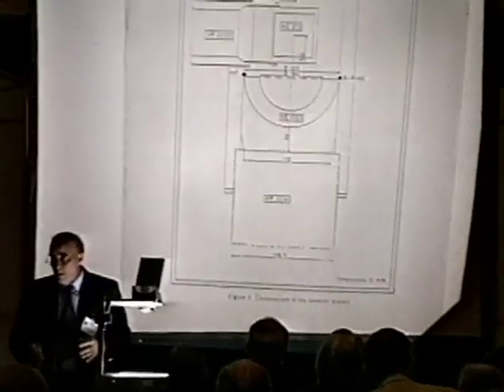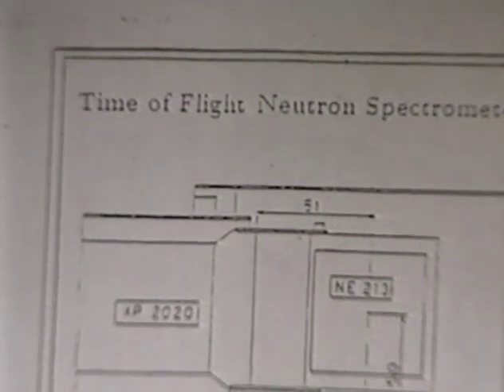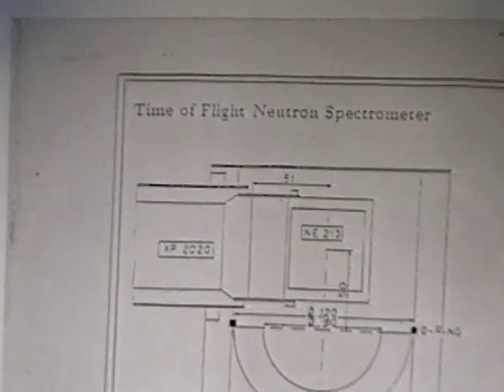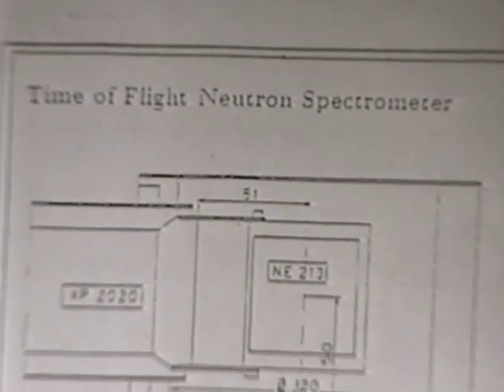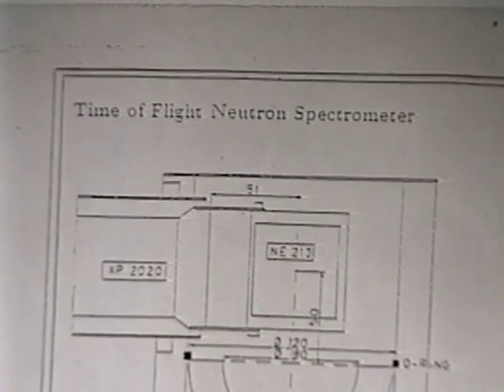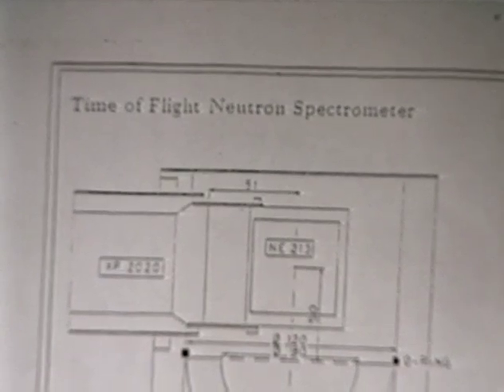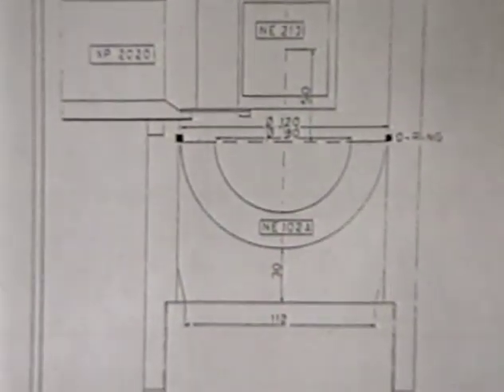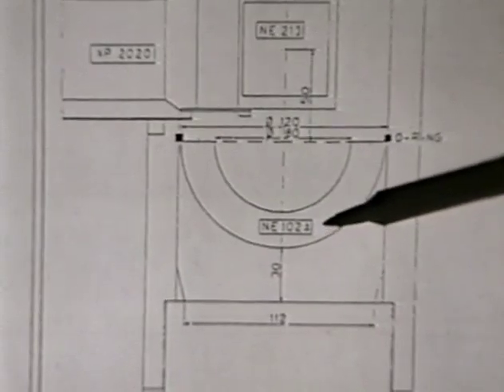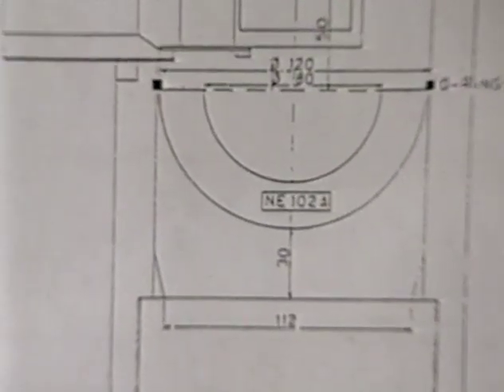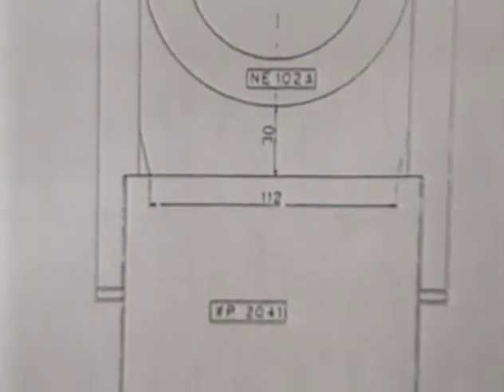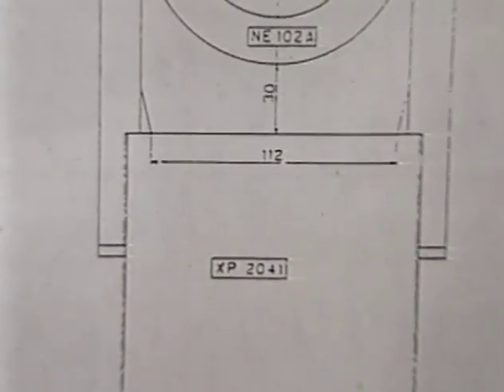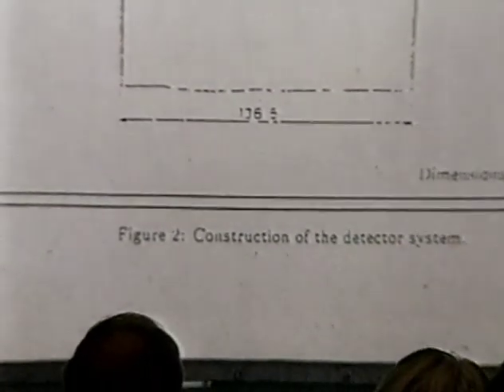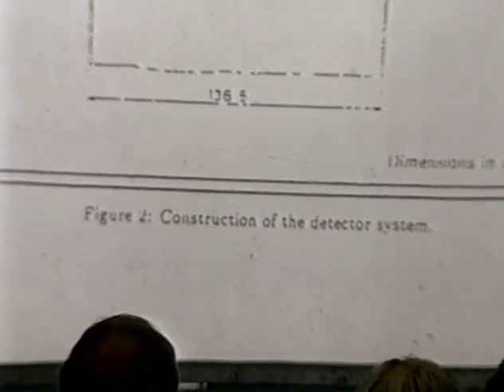We will now consider some details about the construction of the instrument. The construction required a compromise between the manufacturing of the instrument and the performance of the instrument. Practically, the most critical point was the construction of the second detector, the hemispherical detector, which is represented by this shell. This is a shell of NE102A plastic scintillator, which was collecting the radiation scattered from the first one, the scattering detector. The scattering detector was instead a liquid scintillator for neutron-gamma separation through pulse shape discrimination.